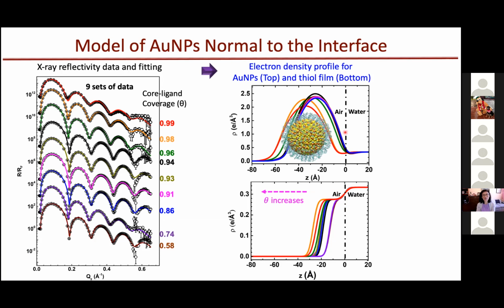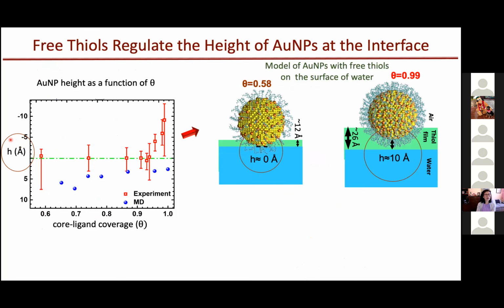As you can see from the electron density, the nanoparticles move away from the water as theta increases, and the thiol film becomes thicker and thicker. From the fitting, we got this H parameter that indicates the height of the nanoparticle relative to the water surface. Below 94% coverage, the nanoparticles sit basically right on top of the water; however, above 94%, the nanoparticles move away from the water quite fast.